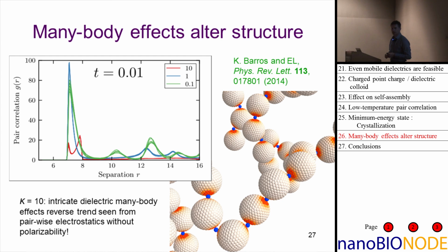So far, so good. But then what? Now there are these dielectric effects. And remember that in this case, the blue particles induce their own attraction. So they bring positive charge to the contact points. But dielectric charge, as I said before, is not created. It's just dipoles that move around. So as soon as that happens, as you get positive charge induced, let's say, on two sides of the particle, then the entire remaining surface of the colloid carries the opposite charge. It becomes negatively charged. It has to be to make the whole surface neutral, dielectrically neutral.